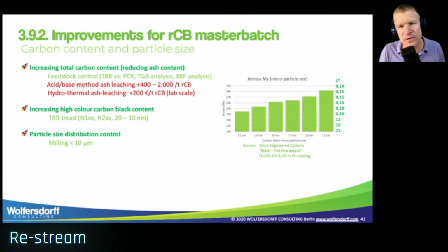And the best and deepest control is with XRF analysis, when we actually measure, and we can do that online. We measure online each tire, how much silica content and other inorganic content it has. There's one recovered carbon black company, Black Bear Carbon, who has a patent for that. And they analyze the tires as they go on the conveyor to sorting. And you might know they have two ranges. One range with normal silica content and one range with low silica content, which of course will be better performing in coloring applications. Now, Black Bear Carbon are specializing on paint applications, but this kind of low silica RCB would be nice for plastic applications as well.